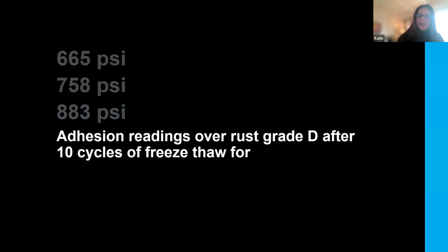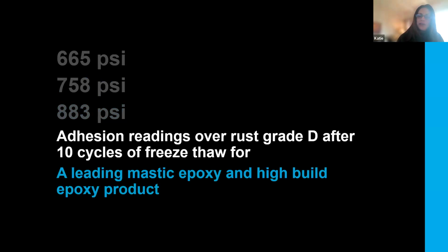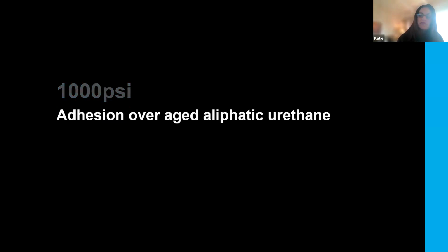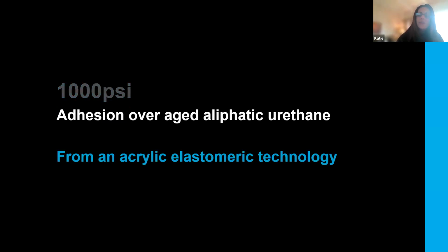665 PSI. There's a number. 758 PSI. Another pretty decent number. 883. These are real adhesion readings over a rust grade D after 10 cycles of freeze thaw. That's from a leading surface tolerant epoxy mastic with a high build capability. So real numbers there over real test substrates. How about 1000 PSI? That's a real adhesion number over an aged aliphatic urethane, also after freeze thaw cycles. And that one's coming to us from an acrylic elastomeric technology. So it is possible to get good results.